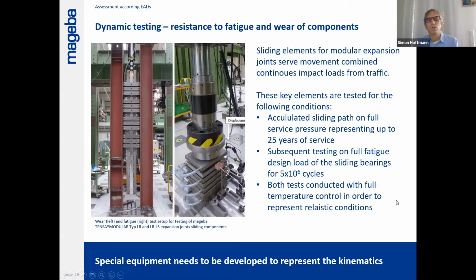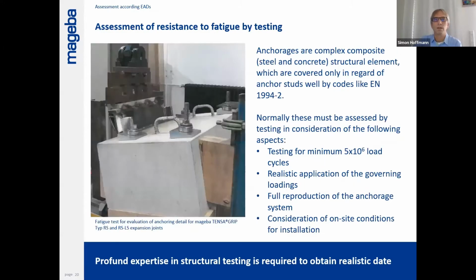These components serve as well for movement, and rather new in ETAG 032 is a combined test where you first have a wear test on that component, and later, after simulating up to 25 years of service, you do a subsequent test with 5x10^6 cycles on full fatigue load, which is a high demand and very well represents the real kinematics, if you have special equipment that needs to be developed in that regard.